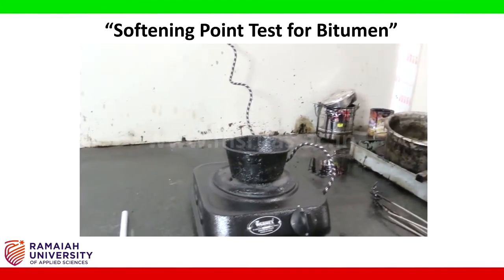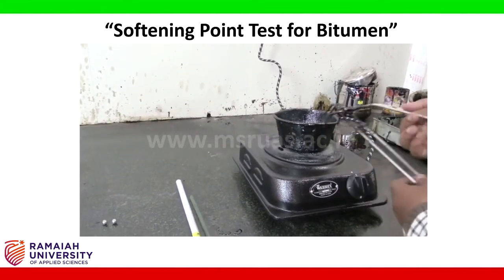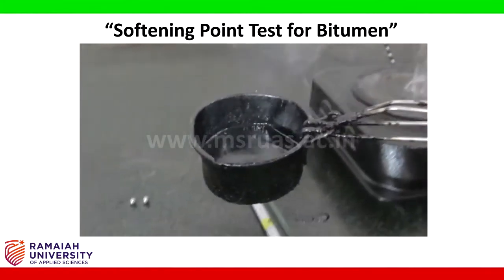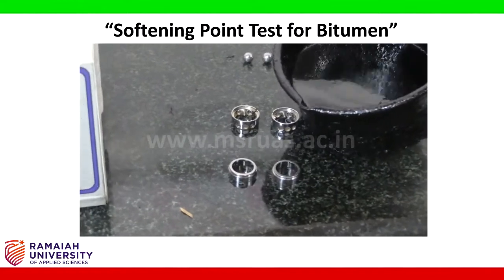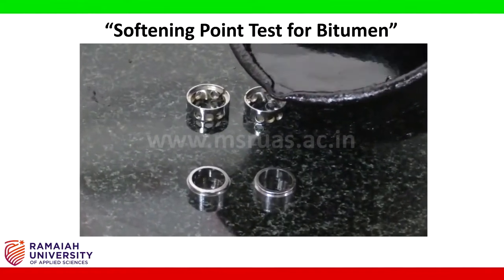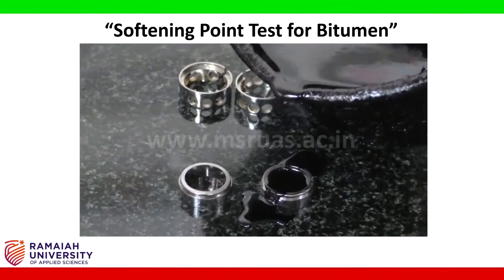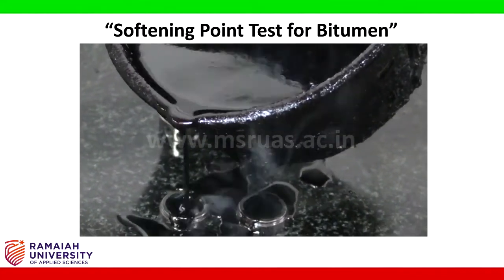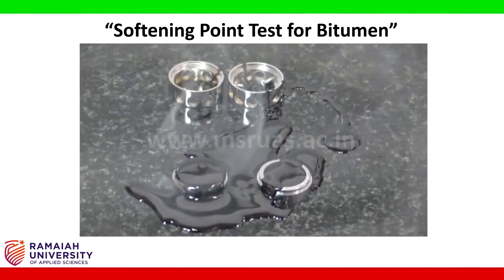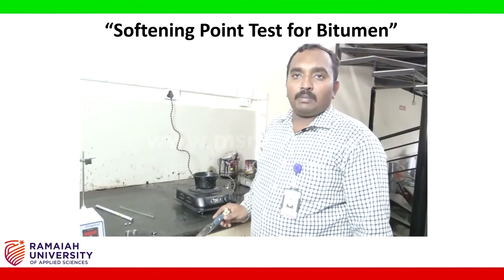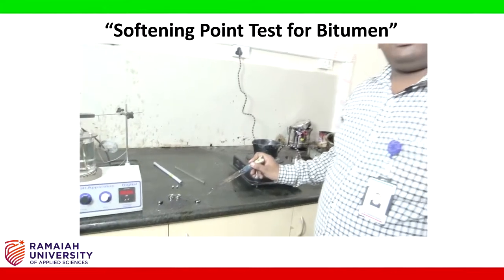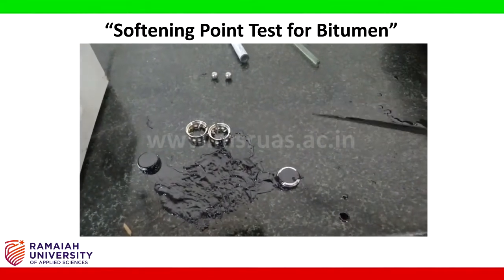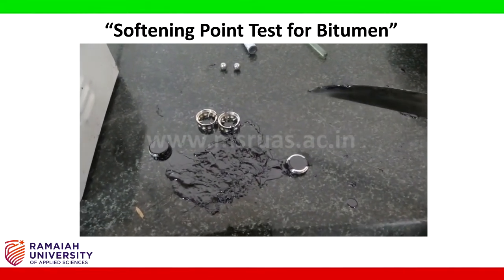We carefully transfer the bitumen to the rings. Make sure to apply oil to the bottom of the ring so there is no sticking. Allow some excess to come out - that's not an issue, as it can be removed after cooling. After placing the rings with bitumen, keep them for air cooling for 1 hour and water cooling for 1 more hour.